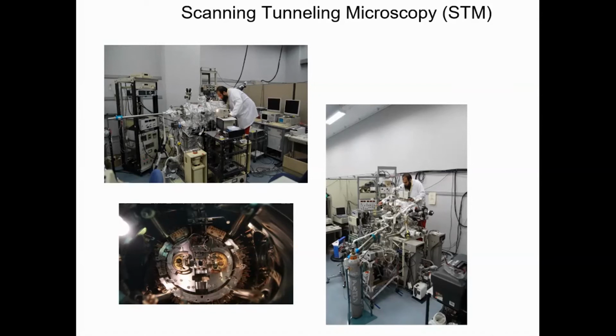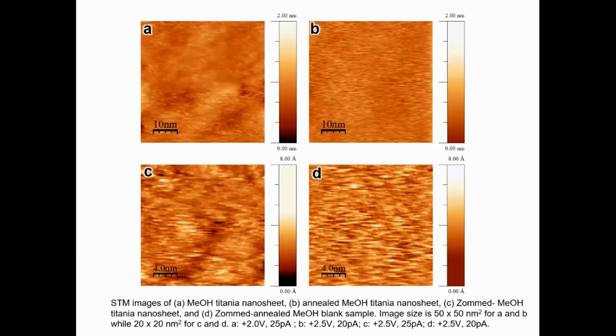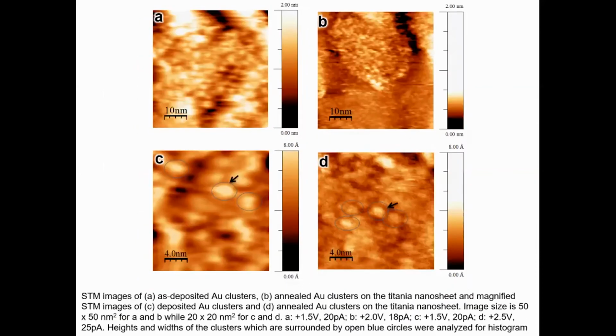And this is why it's giving more high resolution by using the STM itself. We have the titanium nanosheet. We measure them as a reference sample before and after annealing to see what kind of change happened to the substrate before we deposit our Au9. But once we deposit our Au9, we looked at the Au9 before and after annealing.